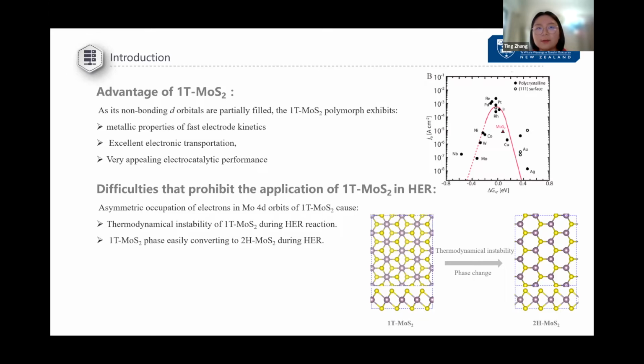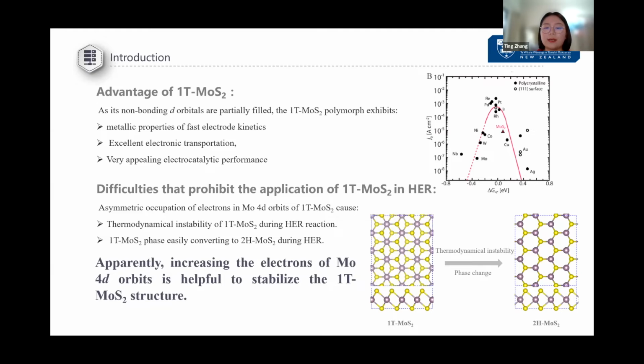Therefore, to obtain high HER activity of MoS2, the key is to increase the content of the 1T-MoS2 phase. To apply MoS2 as the HER catalyst, we need to increase the 1T-MoS2 content, but it's quite difficult because, as I said, there are only 2 electrons distributed in the Mo 4d orbital. That makes the asymmetric occupation of electrons in the Mo 4d orbital. So the 1T phase is quite unstable, and it's really easy to transfer to the inactive 2H phase. To solve this problem, a good way may be to increase the electrons in the Mo 4d orbital and stabilize the 1T phase structure.